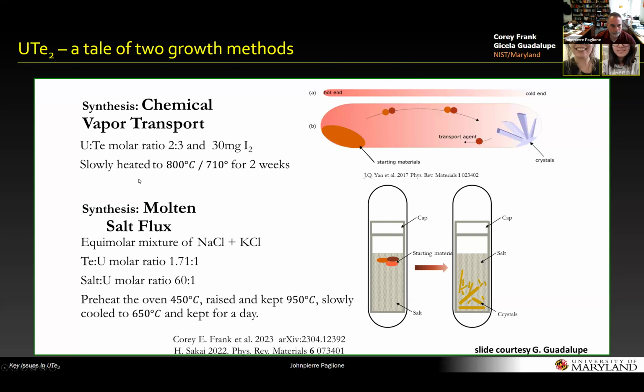The growth, there's different ways to grow these crystals. So far, the vapor transport growth, and as I said, you can tune this temperature and you can get quite different results, at least in the low temperature properties. Or you can use a flux growth, which several groups now have reproduced using sodium chloride, potassium chloride flux with a stoichiometry that's slightly uranium deficient to get superconducting samples. And this has been reproduced even by our own groups as well.